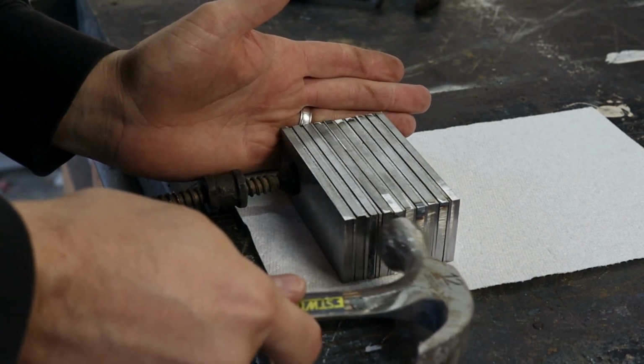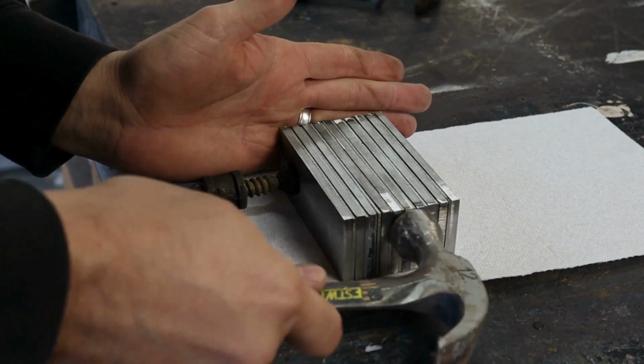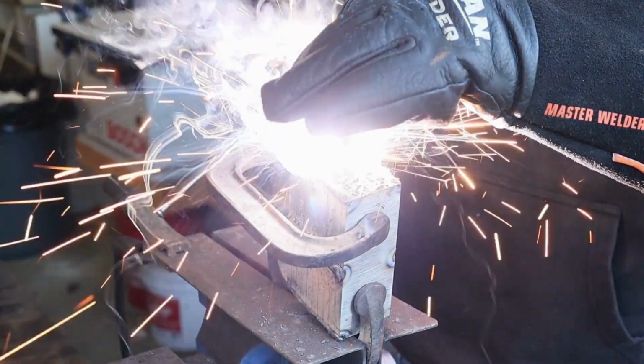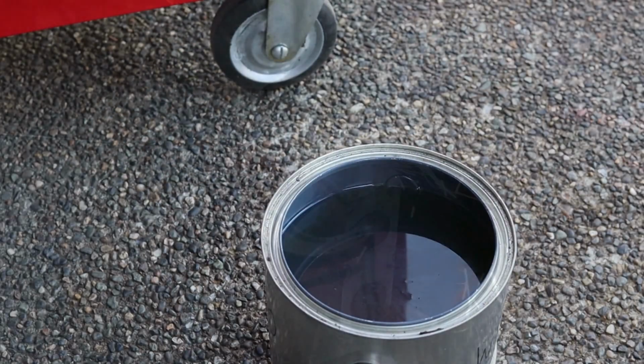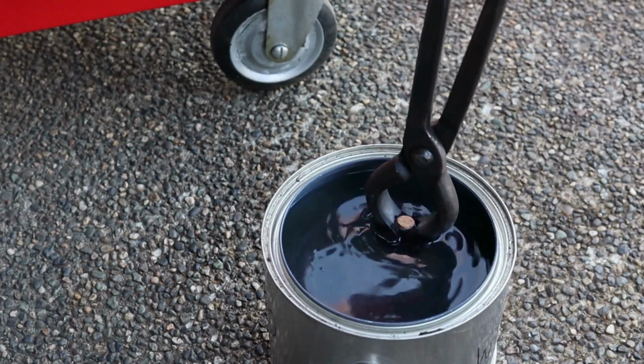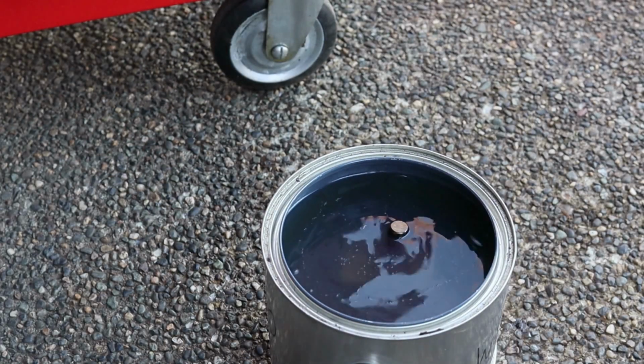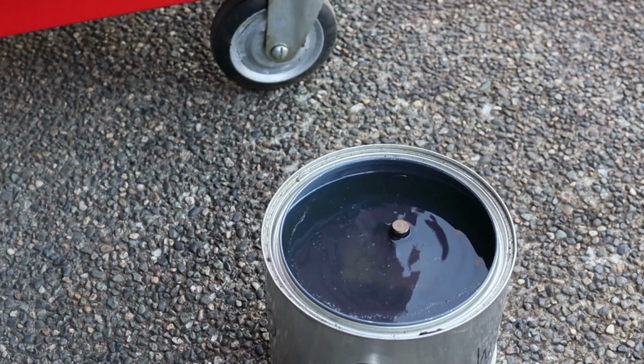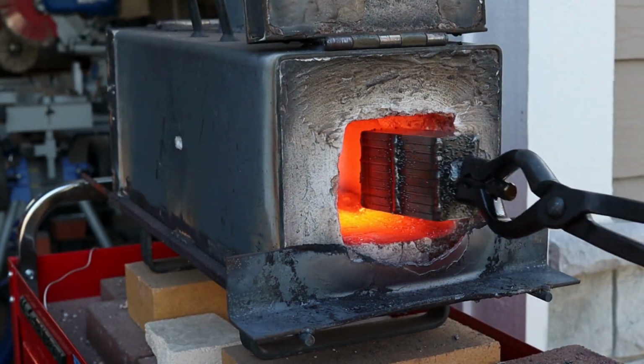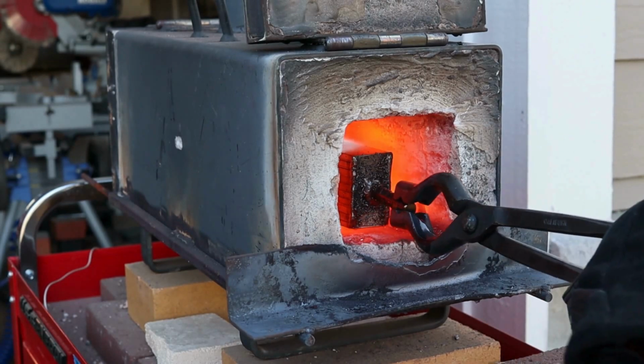into the forge. I've been doing this for quite a while, and as far as I understand it, the oil coats the layers of steel and then burns off in the forge, leaving behind a microfilm of carbon. That layer prevents oxygen from getting to the steel and allowing forge scale to build up between the layers before forge welding. This allows me to get away with not using any flux when I forge weld.